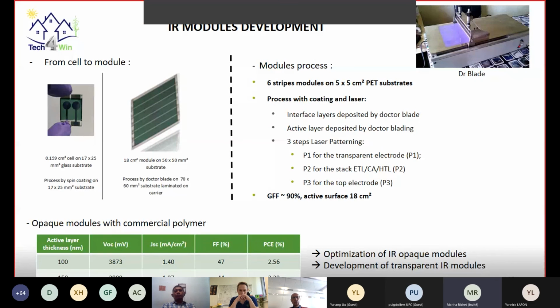After, another try is to develop infrared transparent modules. So from cell to module, the process consists of depositing all the layers by doctor blading. And after, we do 3 steps of laser patterning to design the modules. These techniques allow us to achieve a geometrical fill factor of about 90% for an active surface of 18 square centimeters on samples of 25 square centimeters.